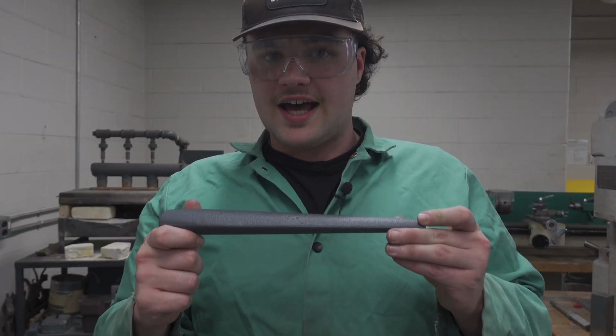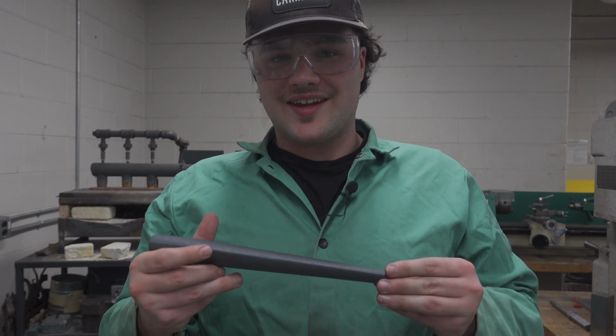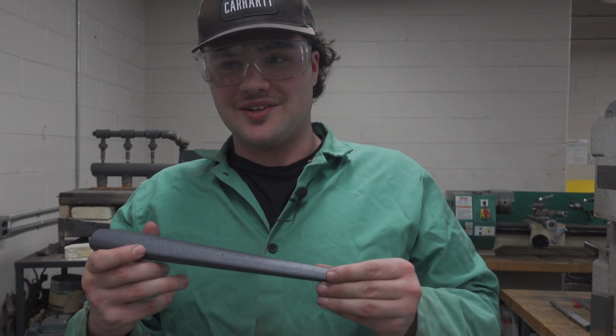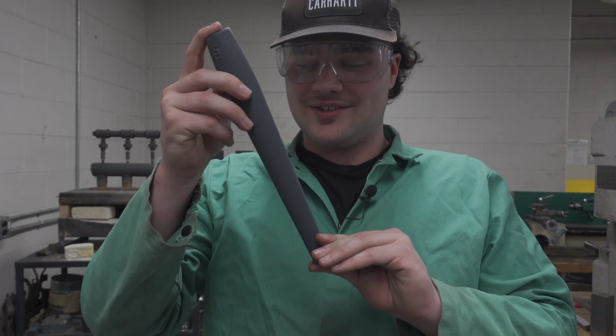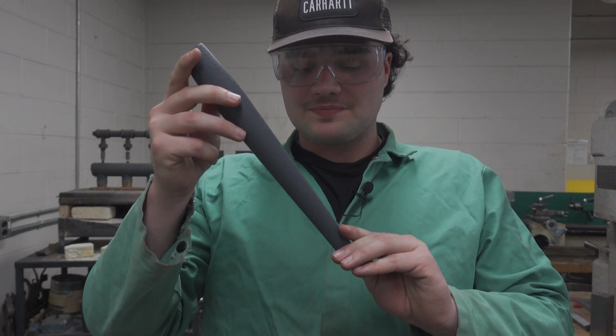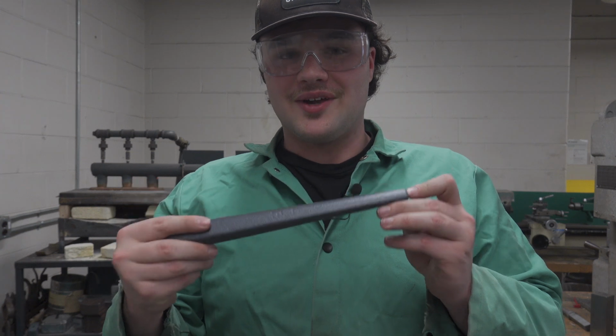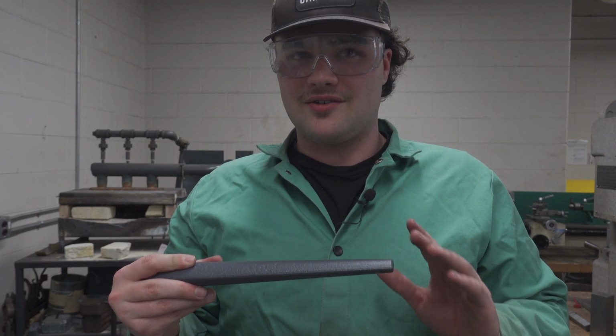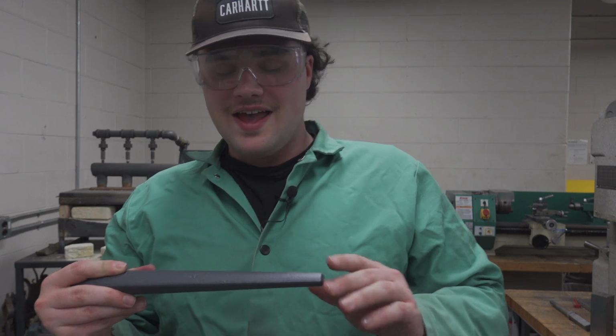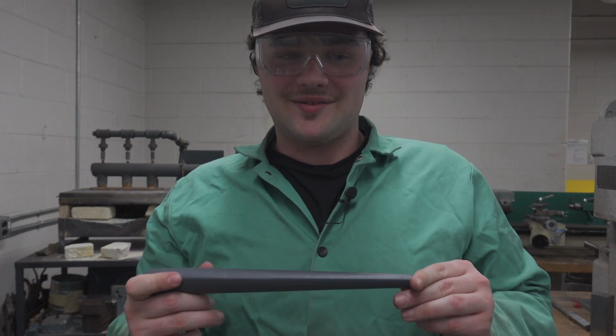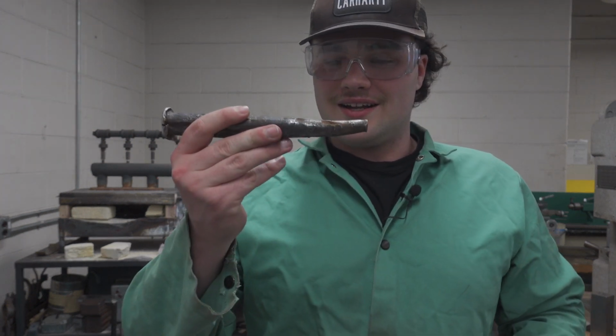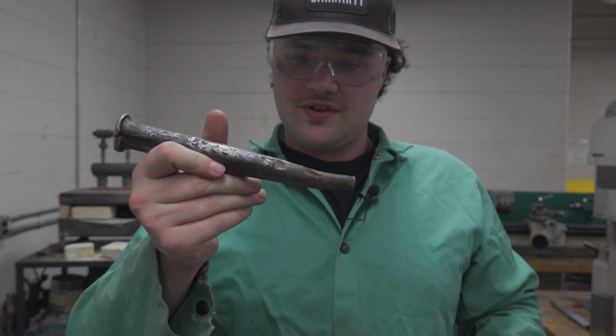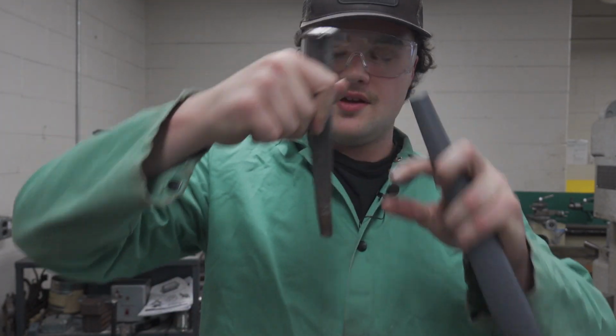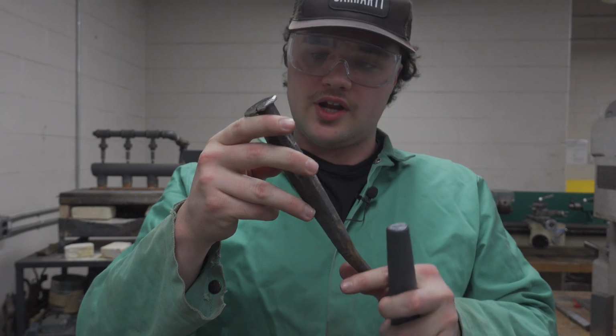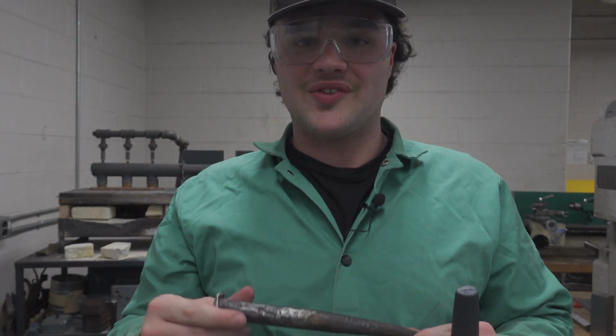One of the funny things I learned is that it's important what condition your material's in. I got these online. Unbeknownst to me, they came in the as cast condition, and we learned that the hard way. This is not the one we actually used to drift our hole. We used one, we got it decently far, way down close to the desired diameter that we wanted it at, and it eventually fractured on us. But luckily we were able to find a more not so well conditioned drift, but it was already up to here, so we were able to get that more smoothened out, and this one is a little bit stronger than the ones I got online.